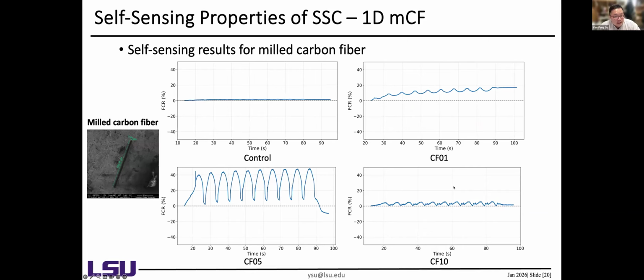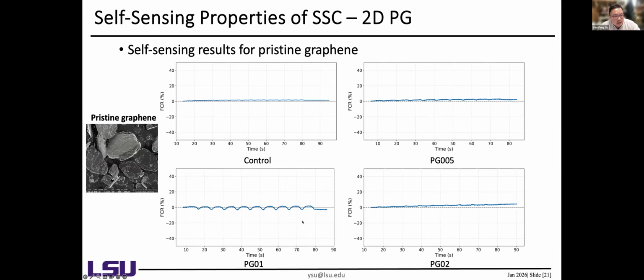Then we switch to the 1D, this milled carbon fiber. So milled carbon fiber, in fact, performs better, especially for this CF05, 0.05%. So we got more stable and obvious signal from this mix. And for the 2D, if our material incorporates this 2D pristine graphene, surprisingly, we got really subtle signal out of these samples. Only PG with 0.1% got a better signal output. So our guess is this type of material, this pristine graphene, if that is not dispersed well, that might cause the signal cannot reflect the change of the structure behavior.